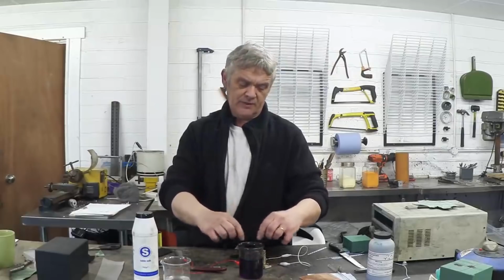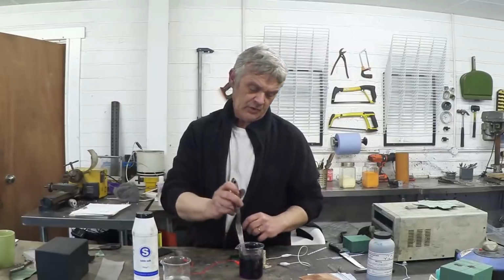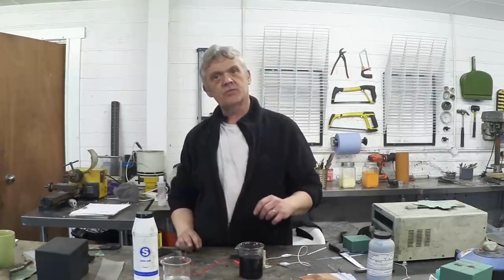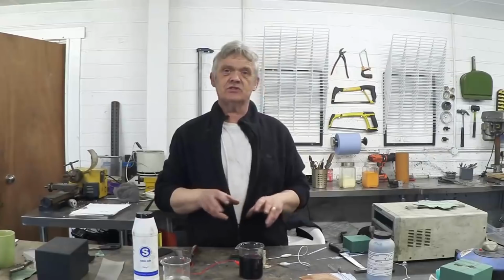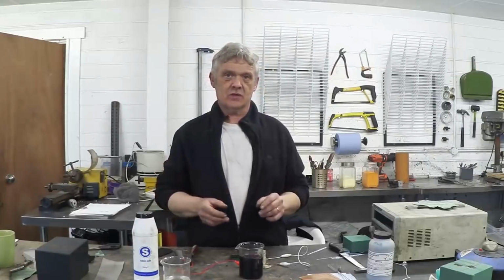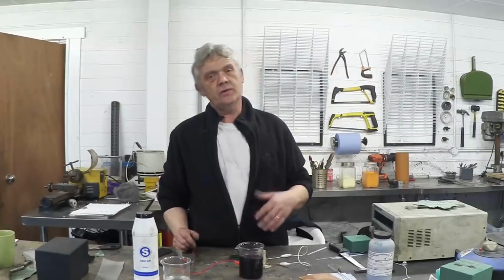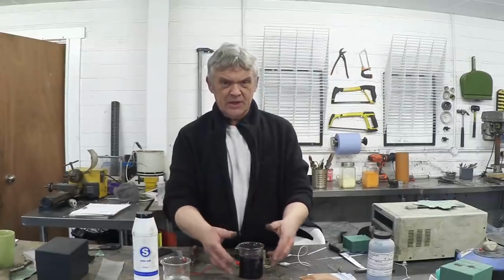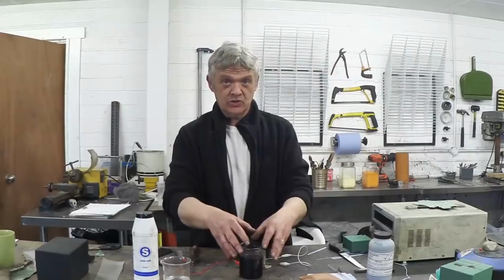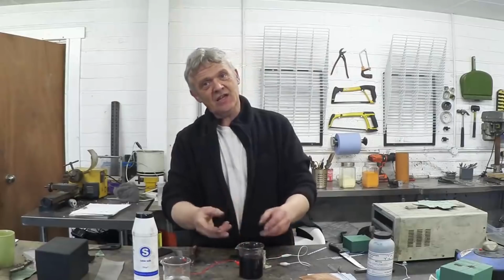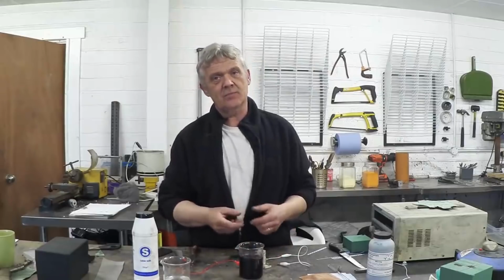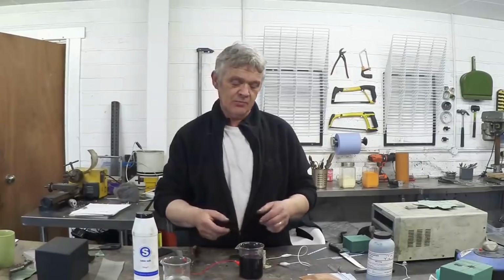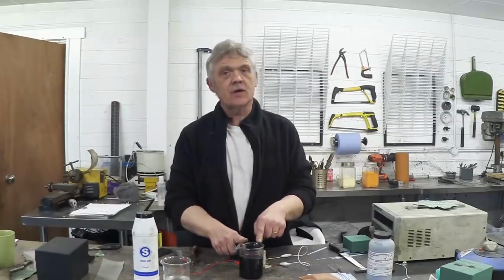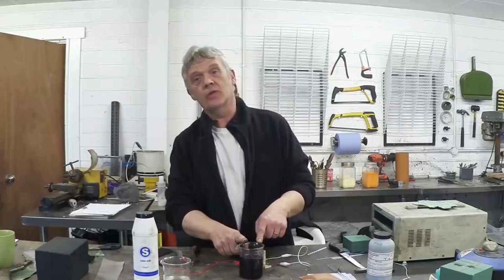So we pop our felt in there and make sure it's covered. Now it won't do it at room temperature. It has to be somewhere between about 60 to 90 degrees centigrade, and you stir that at 60 to 90 degrees centigrade for about 2 hours. That potassium permanganate will be adsorbed onto the surface of the carbon, attack it, and break down to nanoparticles of manganese dioxide. If you make this too strong, you'll get particles of manganese dioxide and they won't work.